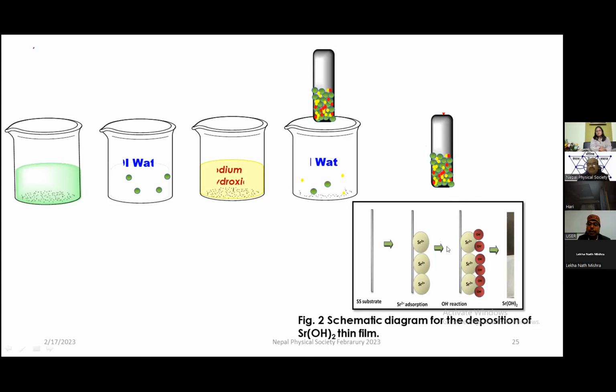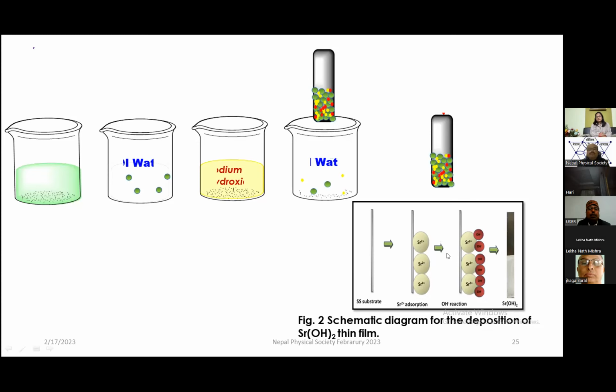So this is the schematic diagram of the deposition of the strontium hydroxide thin film. Once it has been deposited, as I have told you earlier, we have to optimize the time, how much time we have to dip in these two solutions, solution one and solution two, that is the number of cycles. One can start from 10 cycles, then 15, then 20, or one can go to 5 also, and try to see which one is giving the better result.